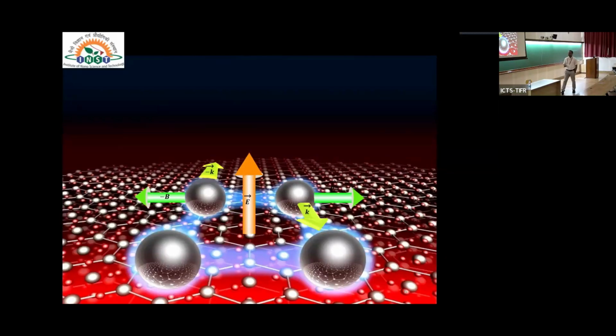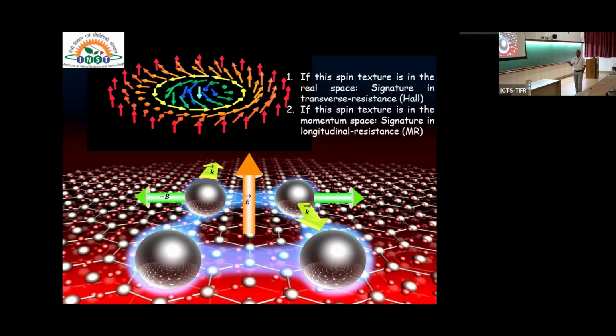This is the kind of slide which represents the overall idea of our work, and many of you have seen this slide. It says that if you have a conducting material, where the conducting particles are moving under the influence of an electric field, the momentum and the spin are locked with each other. But now we ask the question, in addition to this, if you have a non-trivial spin texture, either in the real space or in the K space, then what happens? We are going to show that if the spin texture is in the real space, then it is well known that the signature in Hall or the transverse resistance gives rise to a signature known as topological Hall effect. But if the spin texture is in the momentum space instead of real space, then the signature comes in the longitudinal resistance, that is in the magnetoresistance.